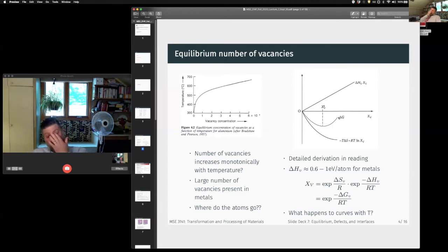Well, we can show this by silicon, right? Silicon single crystals, semiconductors. There's a very low dislocation density. If I heat up a silicon wafer, I don't increase my dislocation density. So what about vacancies is so special? Why do we have an equilibrium concentration of vacancies but not of other defects?